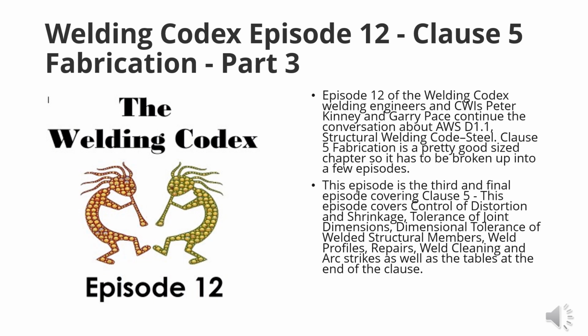I don't have a whole lot to say about it, but if you're going to do it, you better figure it out, because there's a whole lot of reasons on why you have to make sure all your inspections are done, which isn't a big deal. But if you're sitting there deforming the surface, extreme deformation of the surface, you're increasing your surface area and making a lot of sharp ridges for coating failures. So the coating might not grab onto it real well. And here it is, we have to have it approved by the engineer. So I'm sure there's a time and a place for caulking. Like I said, like you, I've personally never dealt with it.